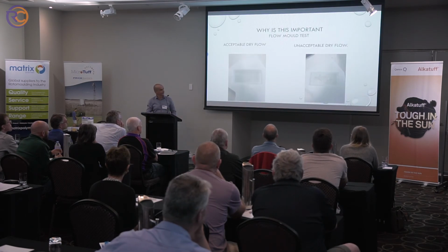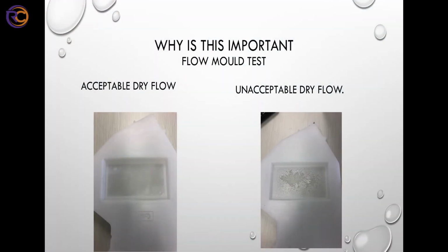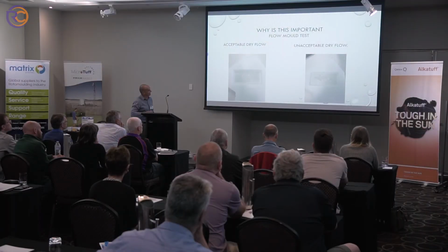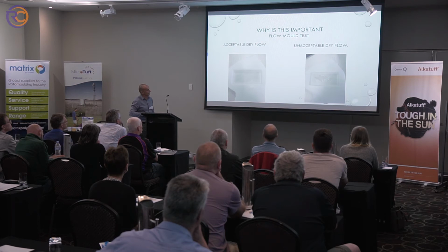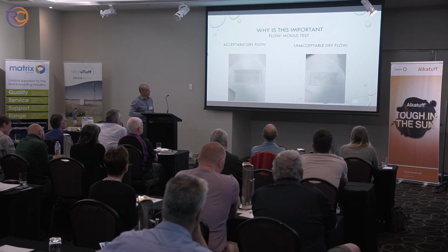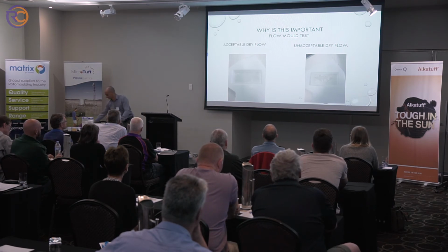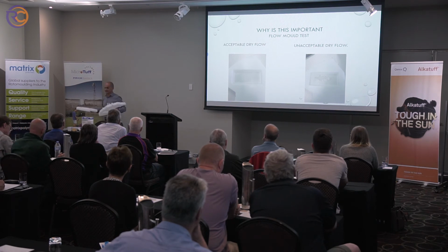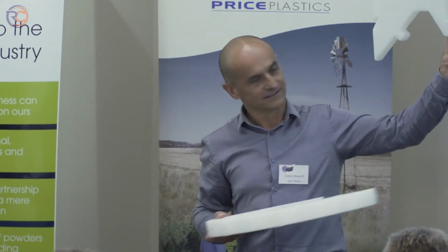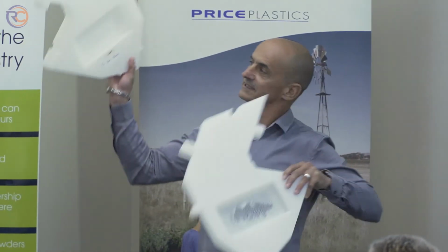So these are examples of what happens when you have an acceptable dry flow and bulk density and not so good. So this mould here is quite difficult to get all the powder into, and you can see what happens if there's not a lot of space for the material to flow around or the powder doesn't have good flow, we just don't get into that area. So again, these are basically the two different materials I showed you. You can see that here there's no material, here there is.